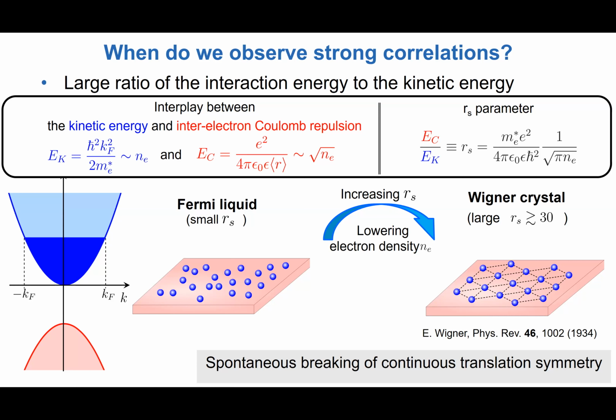Now, with the advent of new materials, this has become possible. So with transition metal dichalcogenides, we as well as another group have actually shown signatures of Wigner crystallization, or formation of Wigner crystallites, at densities on the order of 10 to the 11 per square centimeter. Okay, but this is difficult, right? So getting to this regime where such RS parameter is very high requires very clean samples.